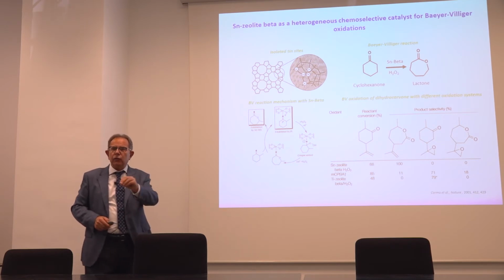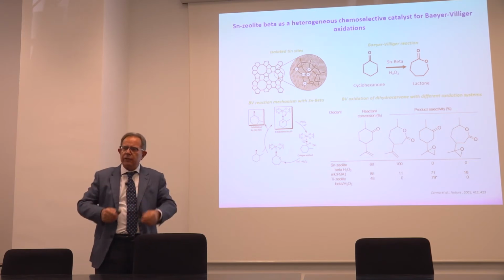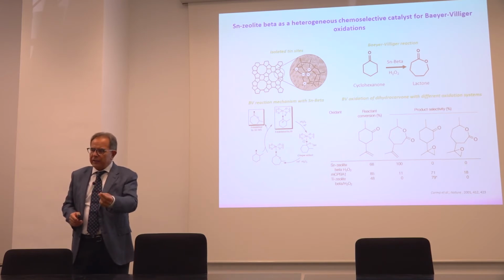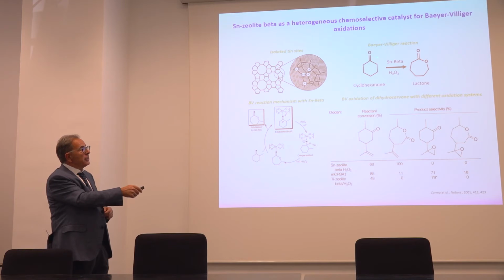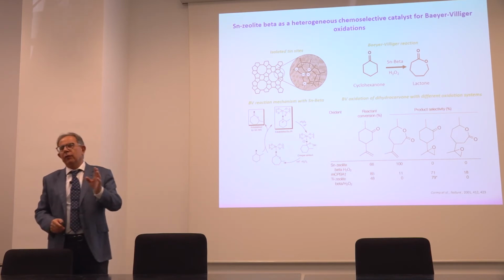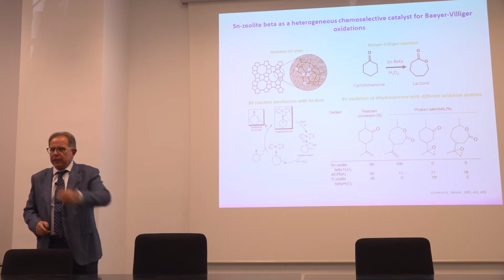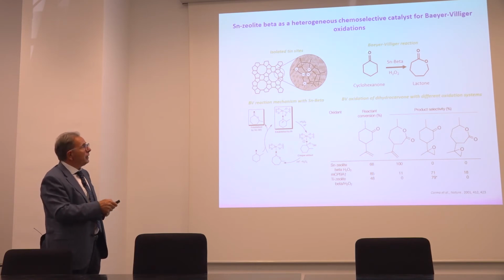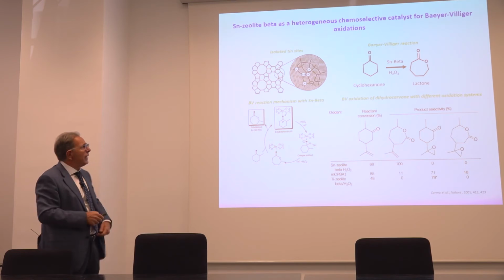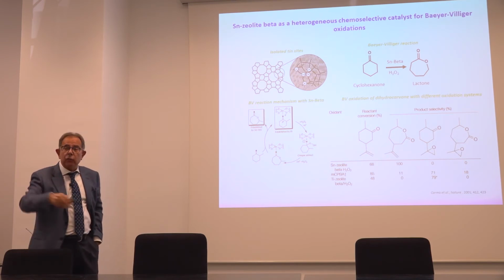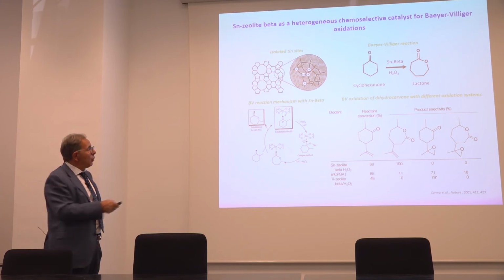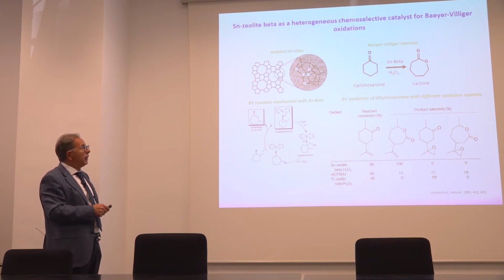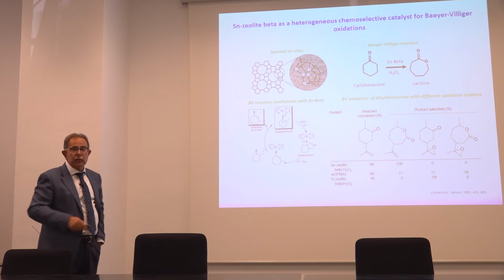And we could activate the carbonyl by introducing a Lewis acid site in the framework of the zeolite, and what we wanted was a Lewis acid site able to polarize this bond, to increase the density of charge here, but at the same time, we didn't want it to form peroxides, because then it could oxidize other groups if we have those groups there. So now, we saw that the one with these conditions was tin, and we introduced tin in the beta zeolite. We could achieve that finally. Tin will polarize that, and we saw that polarization by in situ infrared. And then working with oxygen-18, we saw that indeed the mechanism went through a Criegee-type adduct, and we preserve in the molecule the oxygen of the carbonyl, and the oxygen from the hydrogen peroxide is the one that was introduced into the ring.